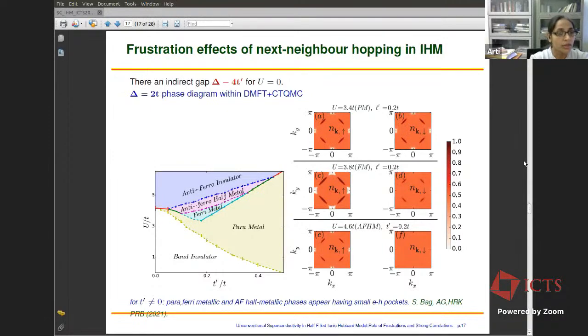To understand that, we calculate the momentum distribution function from DMFT plus CTQMC, which is shown here. And what we see is that in the paramagnetic metal phase, both the up and the down spin electrons have electron pockets around the pi by 2 points and hole pockets around the pi 0 points. And as you tune the interaction strength and go towards the ferrimetal phase, you will see that the electron and hole pockets for one of the spin sectors, for example the up spin sector here, have become much enlarged compared to those for the down spin sector.